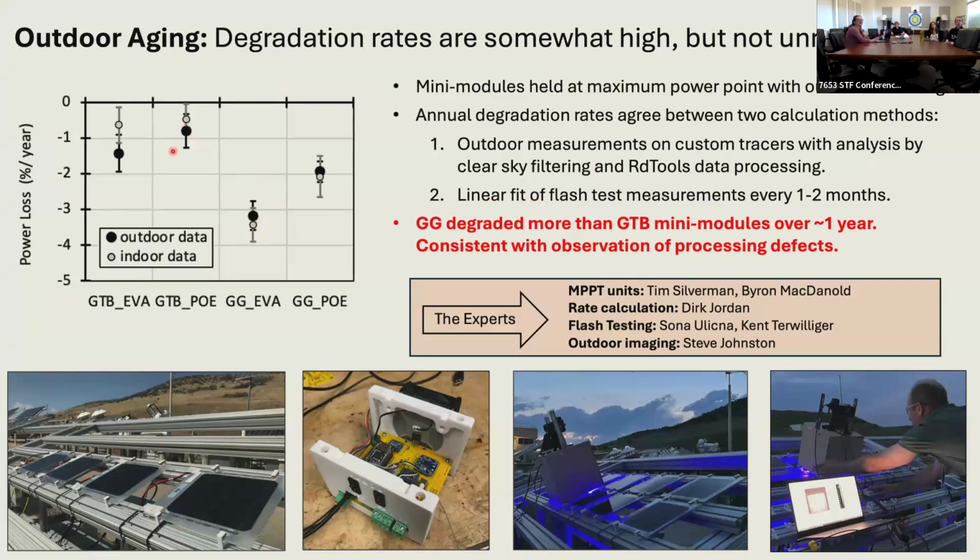So both methods gave similar degradation rates for these modules aging outdoors. And overall, we see there is a slightly higher degradation rate for the glass mini modules compared to the glass transparent backsheet ones. And that's just consistent with those initial processing defects in the glass mini modules.